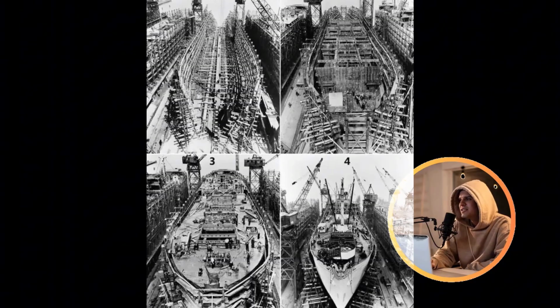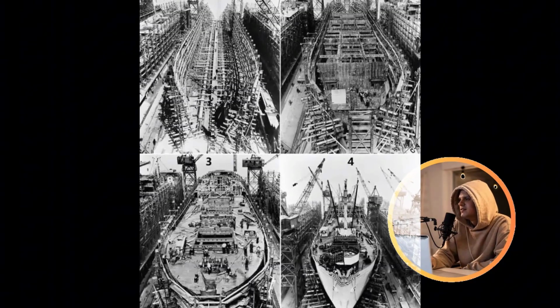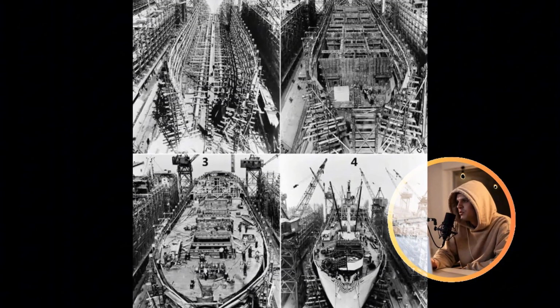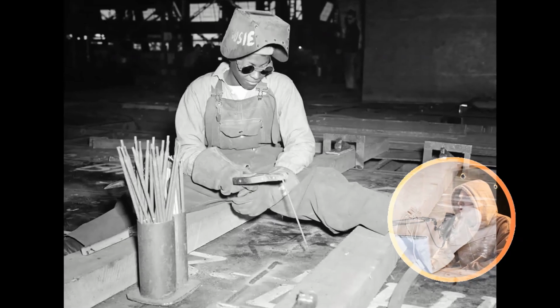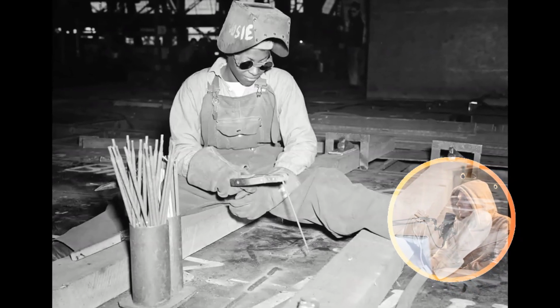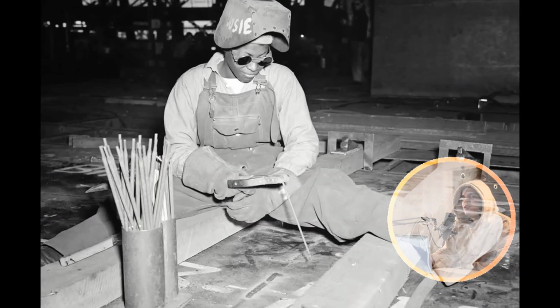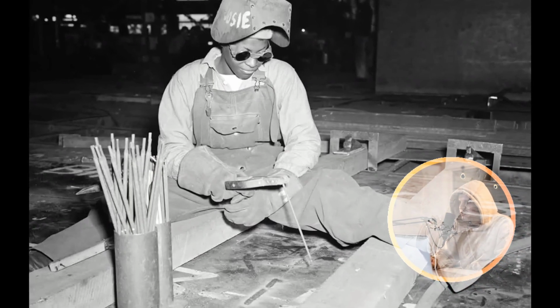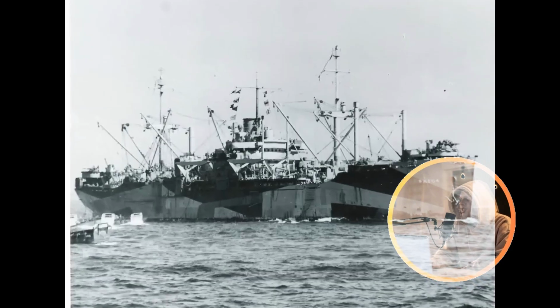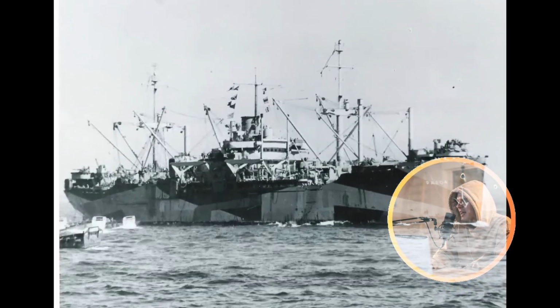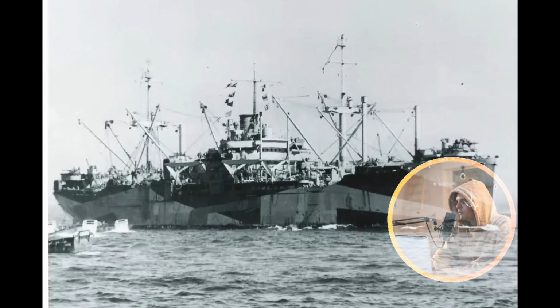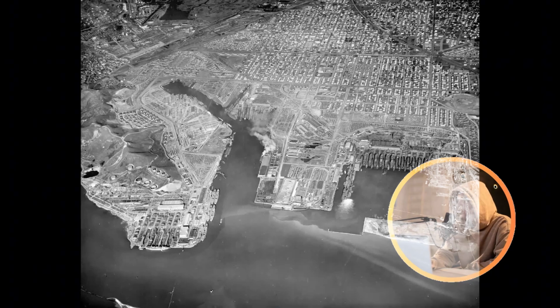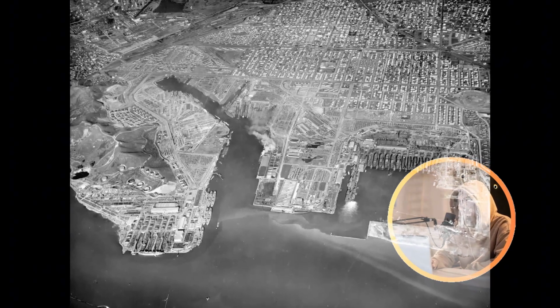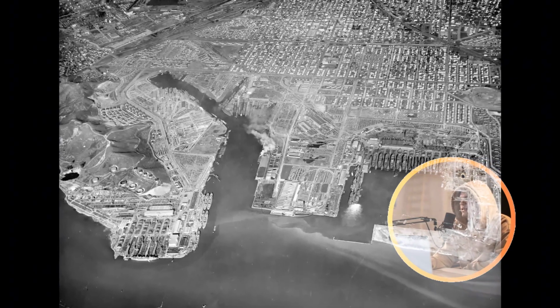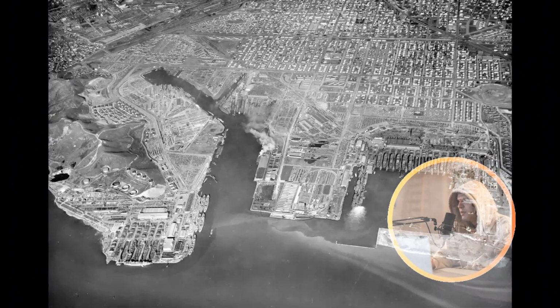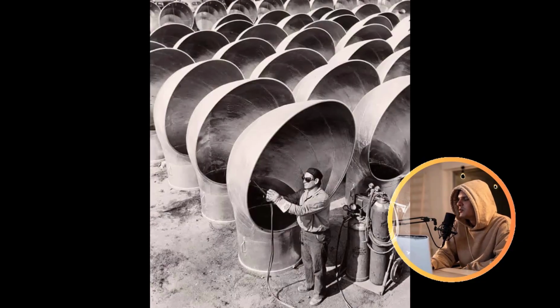Vessels were strictly prohibited from launching until highly trained inspectors had thoroughly certified that every single weld met the exacting specifications. The initial rejection rate was notably high, with nearly 15% of welds failing inspection in the very first Victory ships. However, welders rapidly assimilated the new techniques and procedures. By the middle of 1944, rejection rates had plummeted to below 3%, a powerful testament to the efficacy of the rigorous training programs and the crystal-clear clarity of the newly implemented procedures.